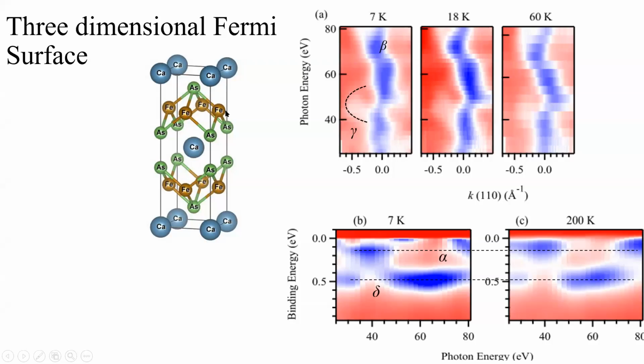In the parent compound, we did not observe any kz dependence. However, in the cobalt-doped compound, I'm calling these bands alpha and delta. The delta band is almost flat as a function of photon energy, and photon energy is related to the kz value. Even the alpha band is flat, so alpha and delta bands are not showing any kz dependence. Here we also see that the beta band is almost flat, so the beta band is also effectively two-dimensional.